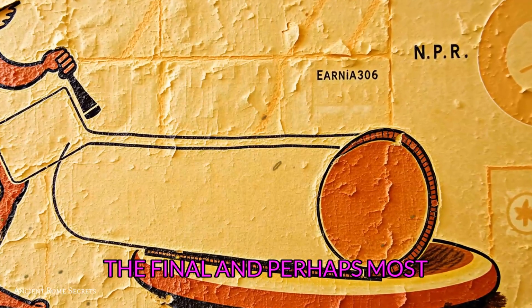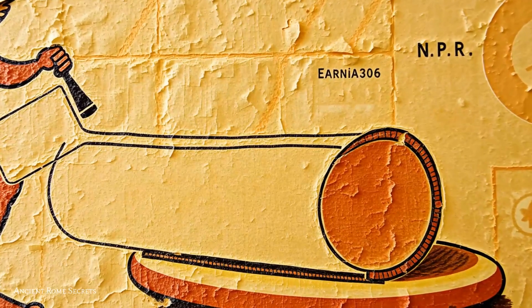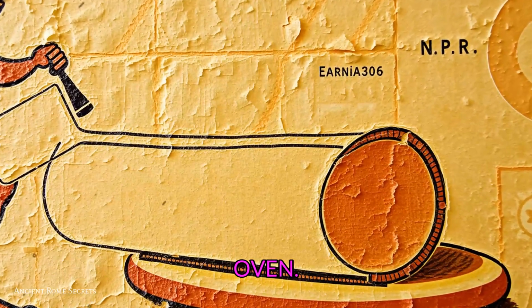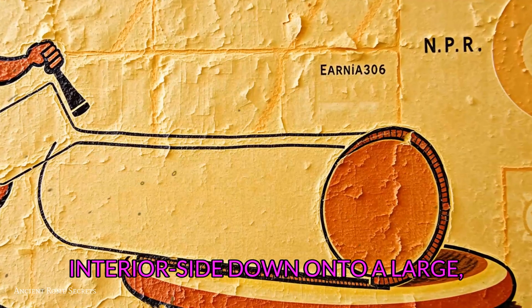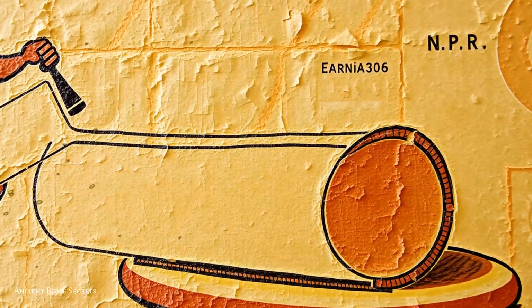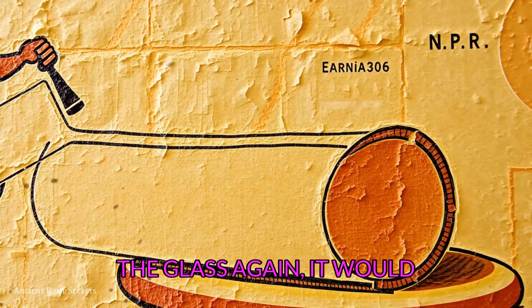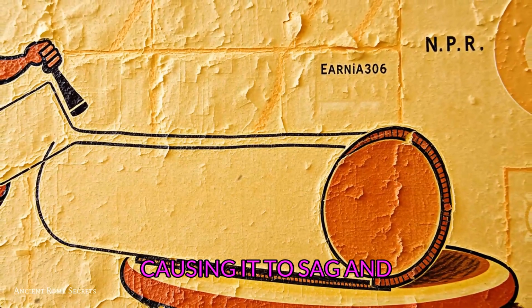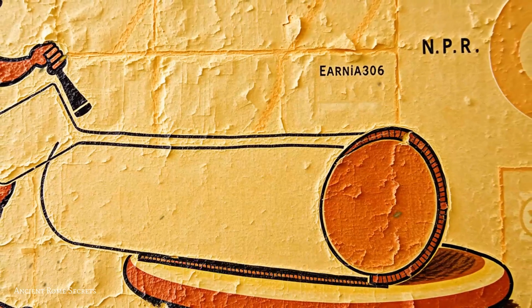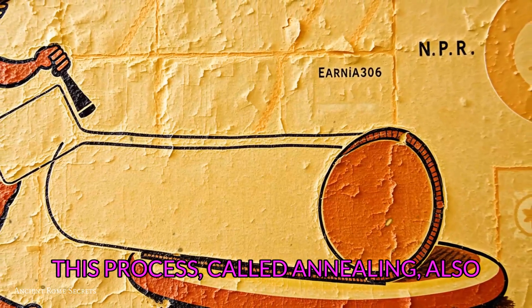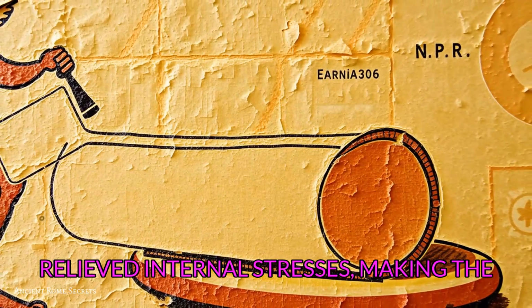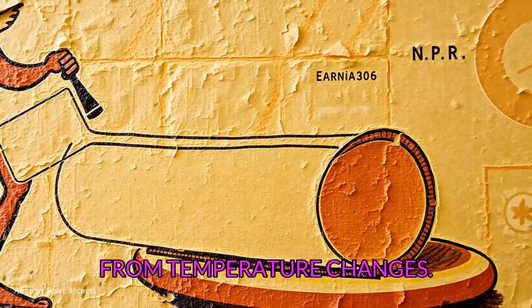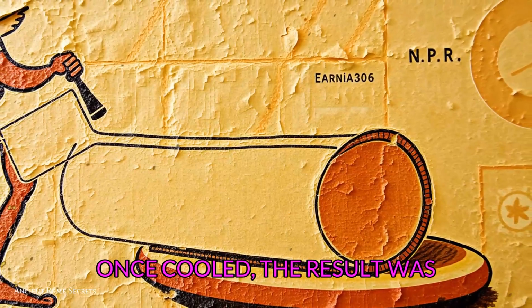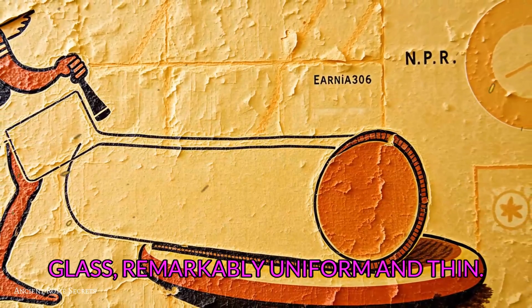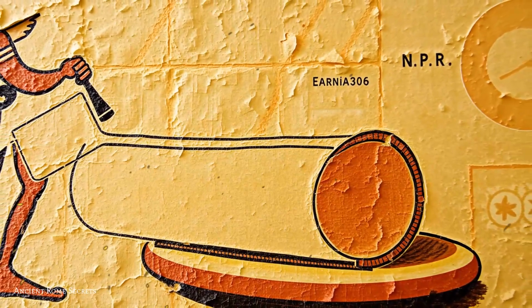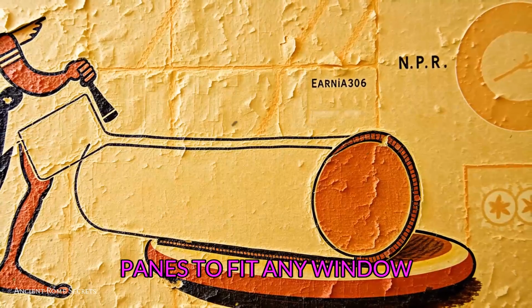The final and perhaps most critical stage was the flattening kiln. This was a special low-temperature oven. The curved sheet was placed interior side down onto a large, flat ceramic plate inside the kiln. As the heat gently softened the glass again, it would slowly relax, its own weight causing it to sag and settle perfectly flat against the ceramic surface. This process, called annealing, also relieved internal stresses, making the pane less likely to shatter from temperature changes. Once cooled, the result was a large, rectangular sheet of glass, remarkably uniform and thin. It could be cut with a hot iron into smaller panes to fit any window frame.